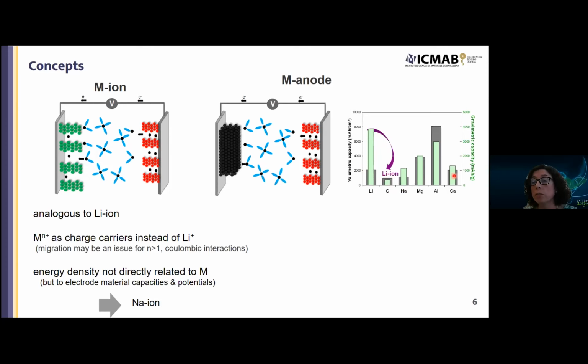So you see that one could have interesting figures of merit for all those metal anodes, especially for aluminum, considering that you would exchange 3 electrons per each ion. And the energy density is the product of the voltage and the capacity. So let's have a look at the standard redox potential. And for aluminum is intermediate, magnesium is somewhat lower, but calcium has a very low value very close to lithium. So in principle, one could expect a very high energy density for calcium negative electrodes, and then one would have to look for very good positive electrodes to match those capacities.